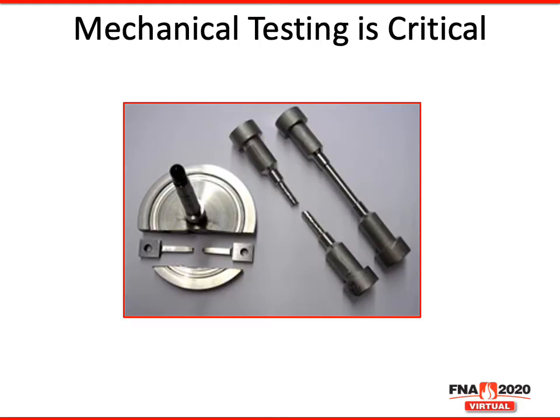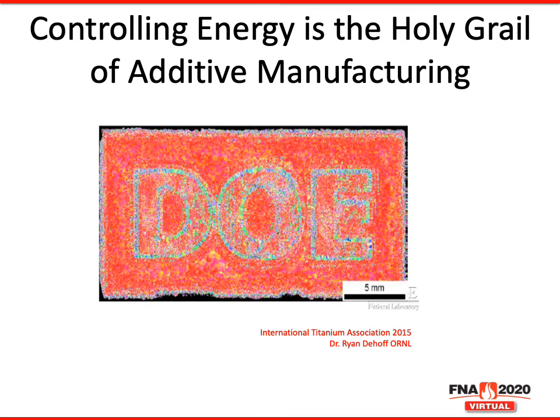Mechanical testing is also very critical. An amorphous structure which has no longitudinal or transversal grain orientation, so having these test bars in every load is very critical to the final part. Controlling the energy is the holy grail of additive manufacturing. This particular slide shows a piece of Inconel that's 2 inches by 4 inches. By controlling the energy, they're able to flip the grain orientations to spell DOE, or Department of Energy. This was built for design by the Department of Energy.